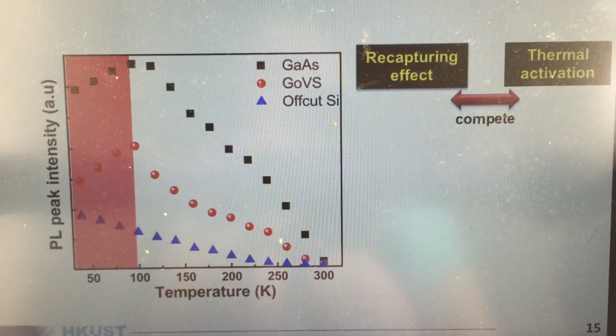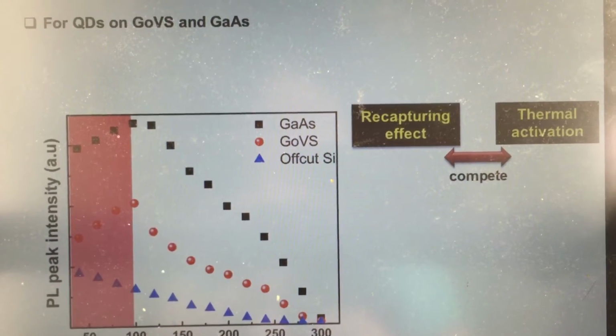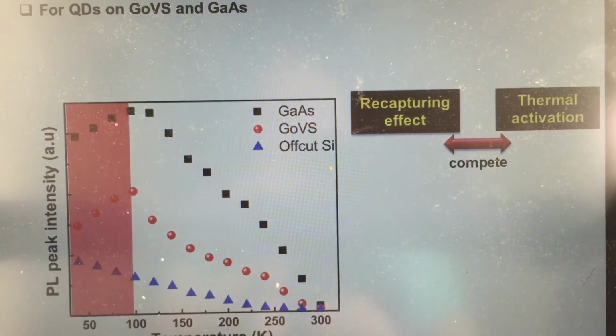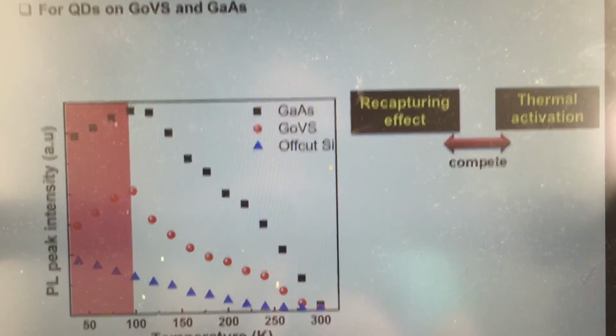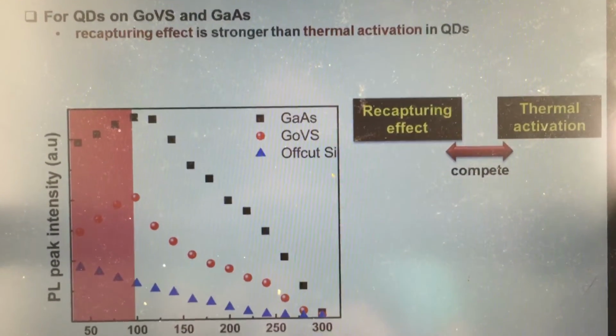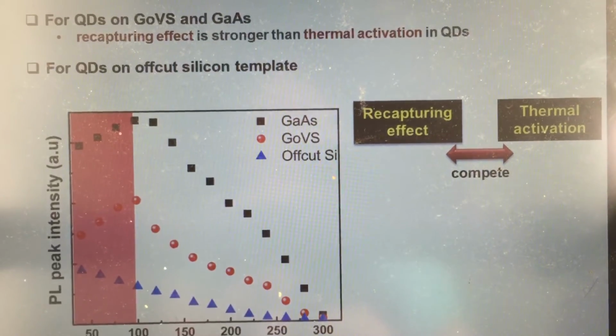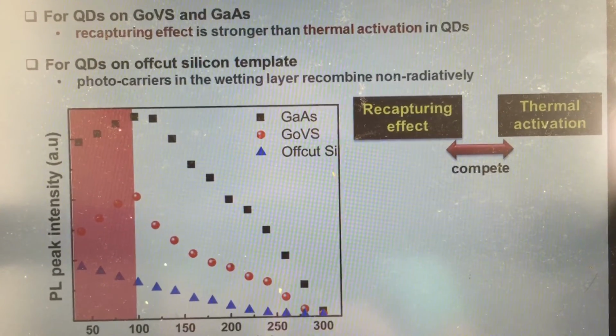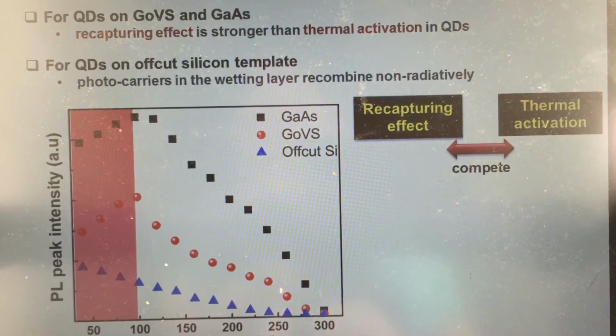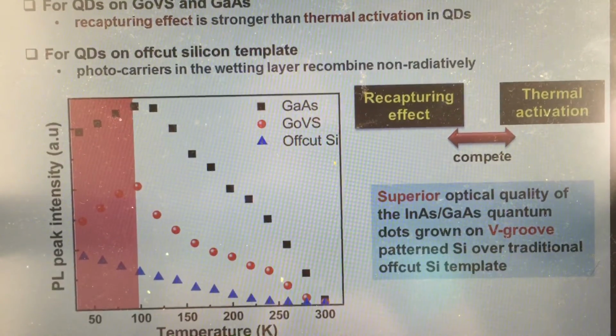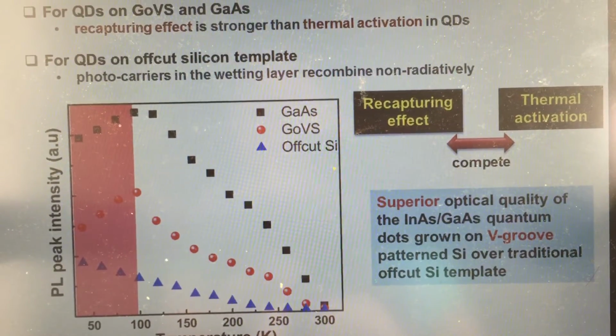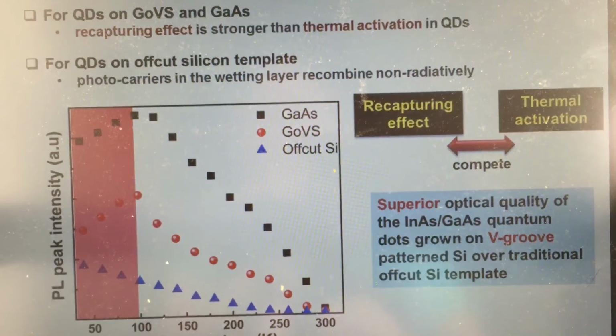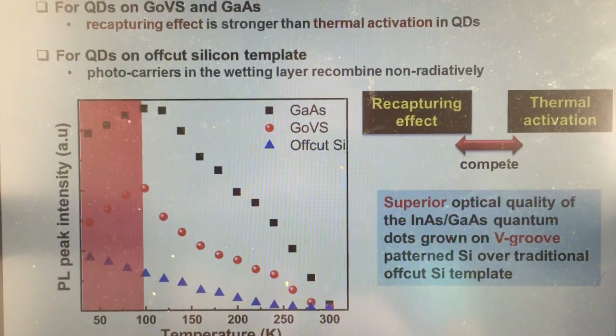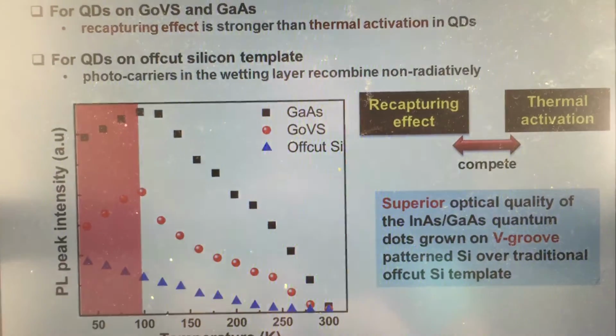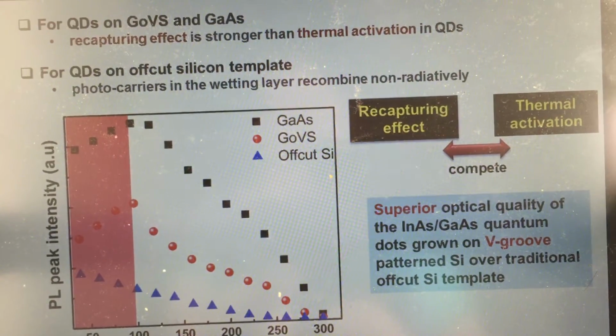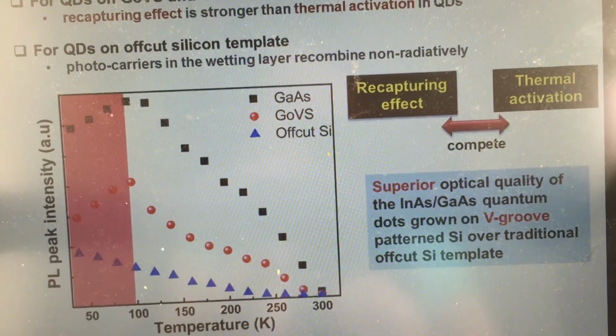And so, in this low temperature range, for quantum dots on GoVS and GaAs substrates, the recapturing effect is stronger than thermal activation, which leads to an increase in PL intensity. However, for quantum dots on the off-cut silicon template, the photocarriers in the wetting layer recombine non-radiatively instead of relaxing into the dots. So we can see continuous PL quenching as a result of the large density of defects present in the active region. Through all the PL analysis, we have demonstrated superior optical qualities of the quantum dots on the V-groove structure compared to the off-cut silicon template.